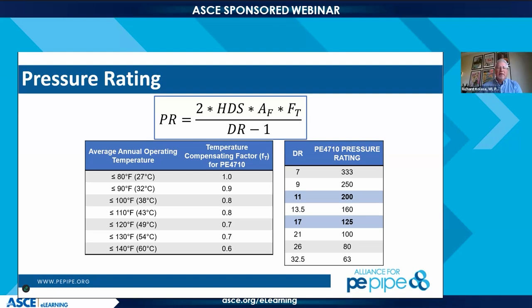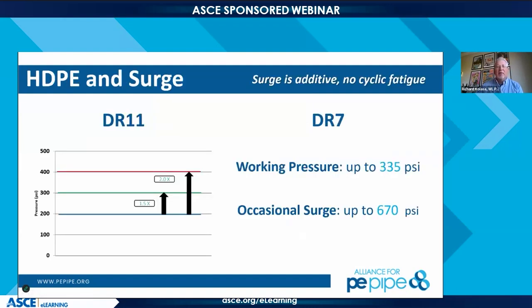So that's correct, Alan. And just one aspect of that, understanding this formula is important for, I know there was a question on hydrotesting the product. So if you hydrotest above ground, you need to take into consideration if that pipe got really hot. Let's say you were on a typical warm day in Florida and that pipe was sitting out all day and it got warm and the fluid inside also got warm. You can still hydrotest it to 1.5 times if that's the number that you're testing at, but you just have to derate it in accordance to the temperature of that fluid and the condition of the pipe. You're still testing at that 1.5 times, but it just needs to be derated.